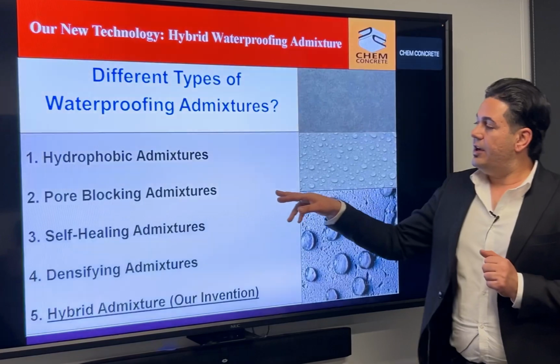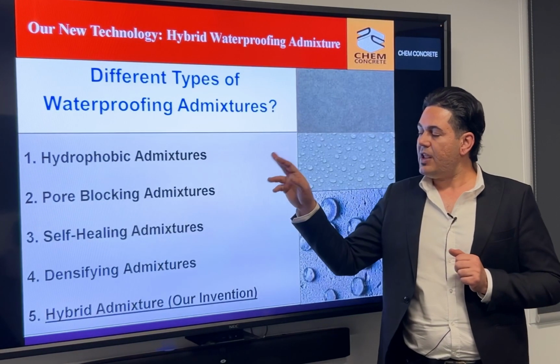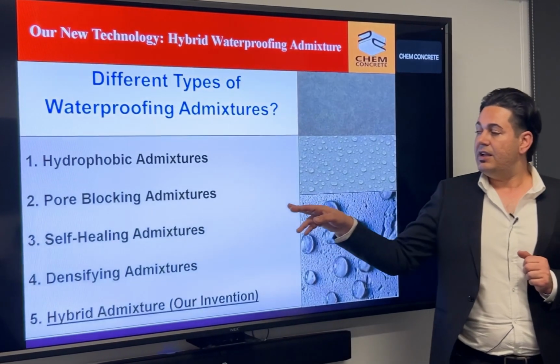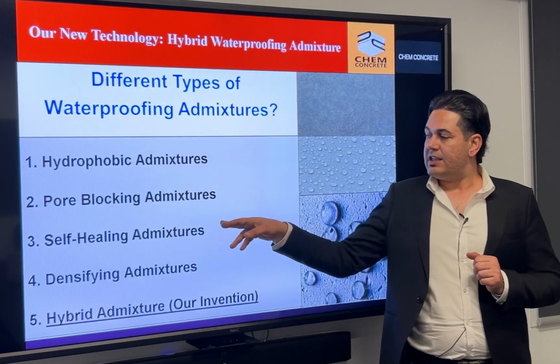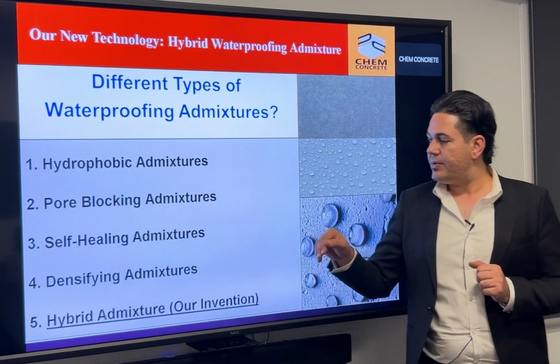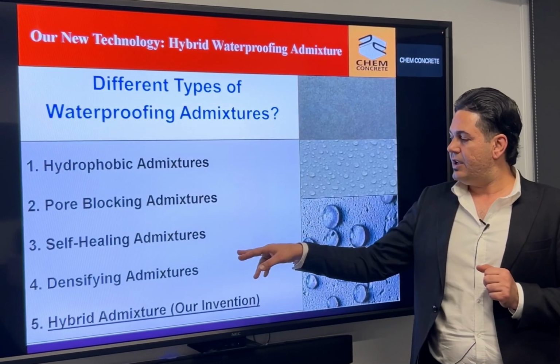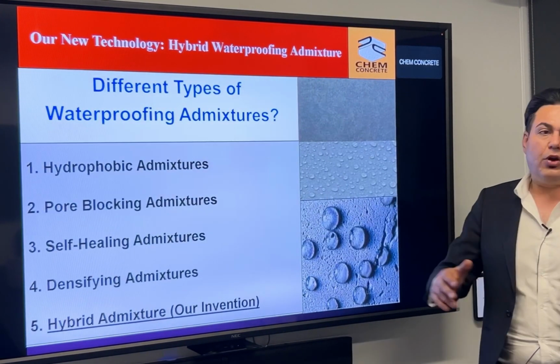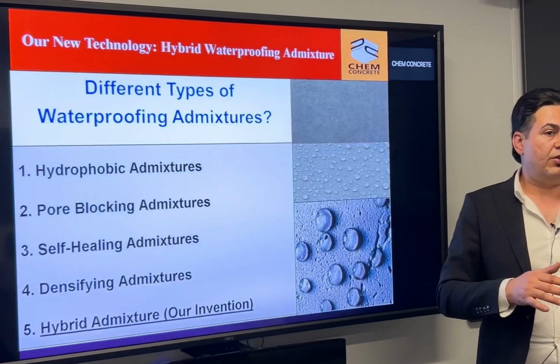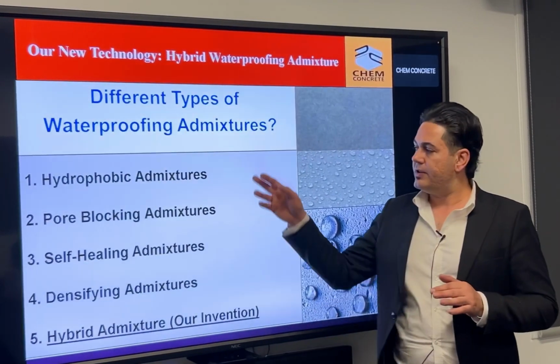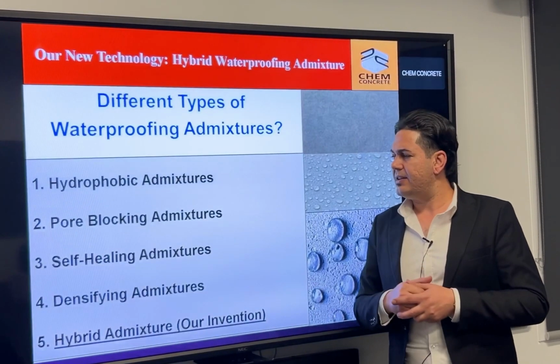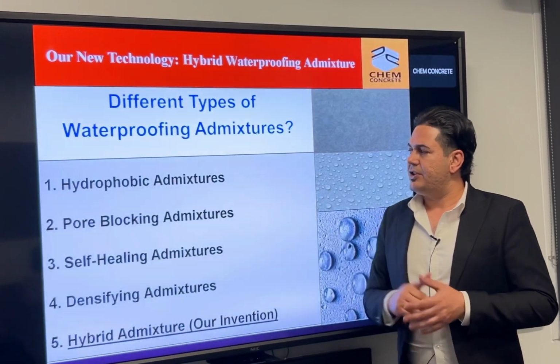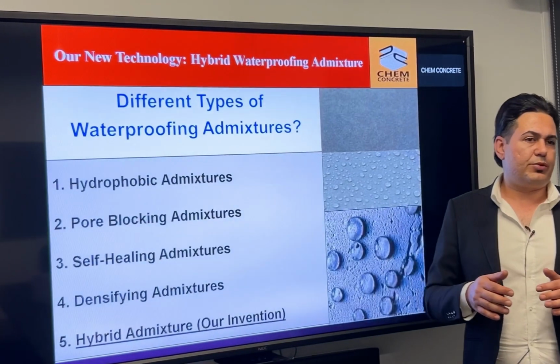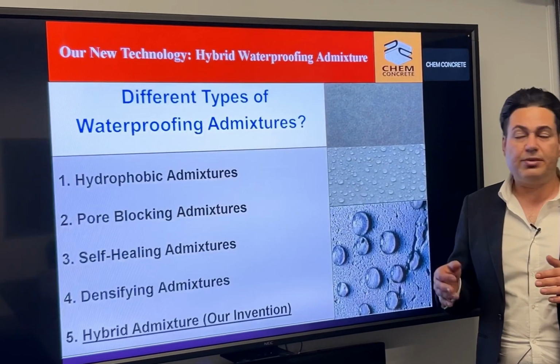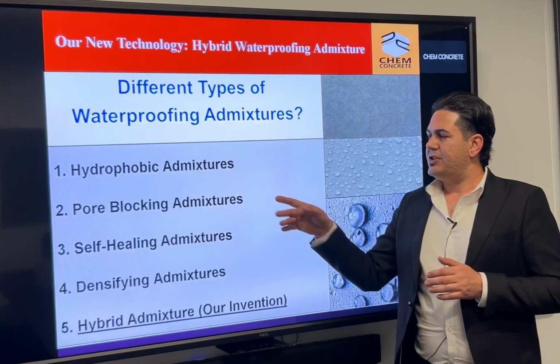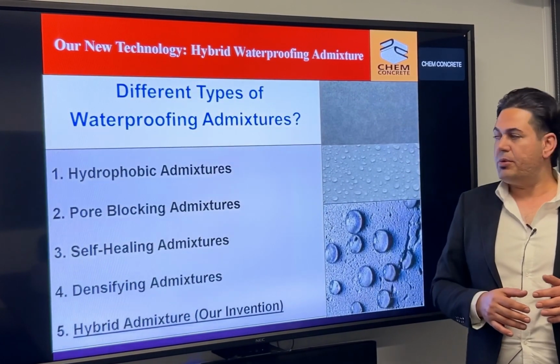The next group is pore blocking admixtures. The next one is self-healing admixtures. Crystalline admixtures are also classified as self-healing admixtures, and then densifying admixtures. While doing all the testing, literature review, and studying all the publications that have been done so far on these types of admixtures, we noticed that in the case of hydrophobic admixtures, in the best case they could reduce the water absorption by up to 18% to 20%. In the case of pore blocking admixtures, up to probably 15%.